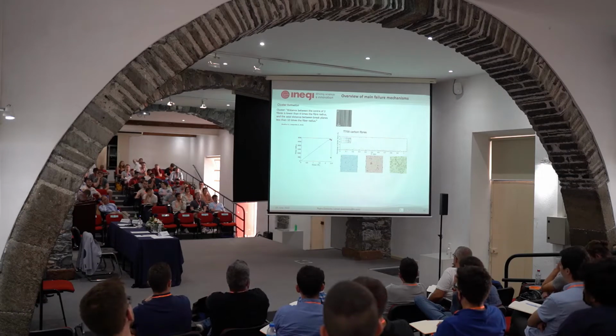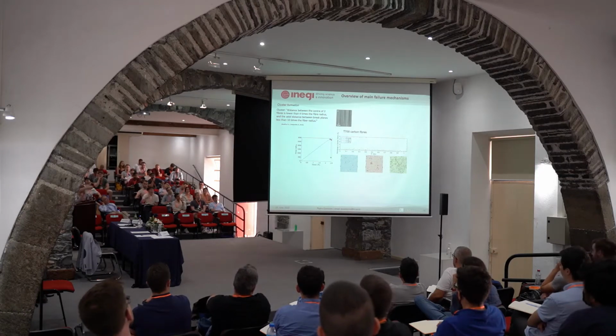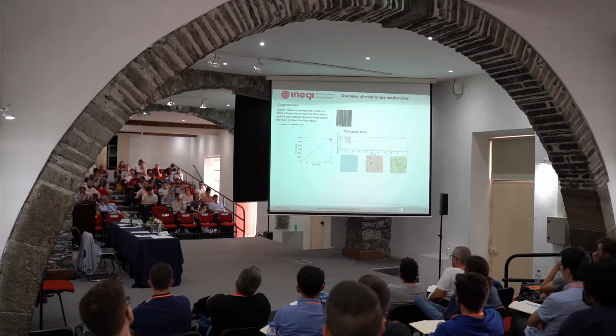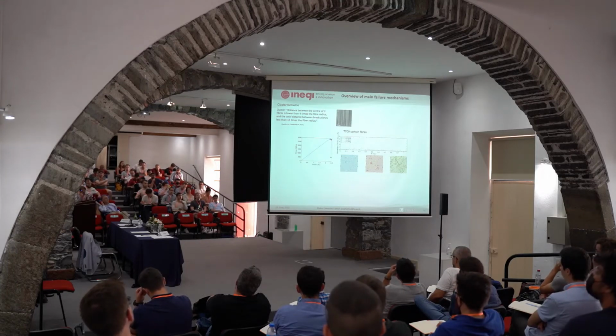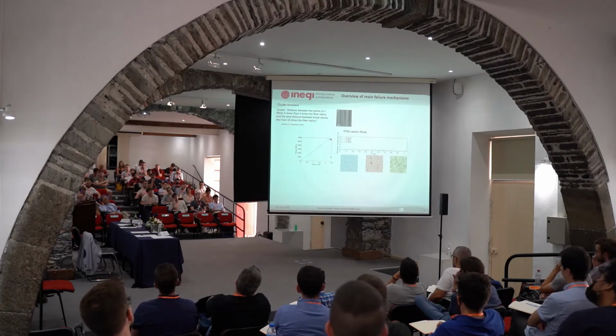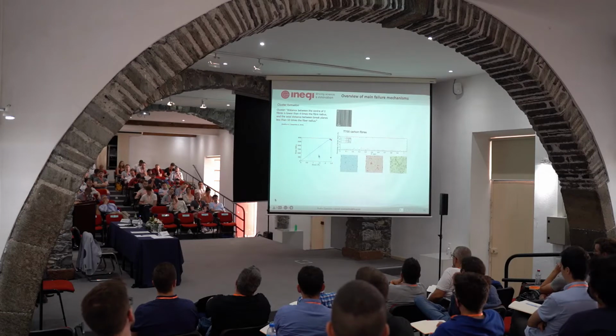So what you can see, even from that picture that was obtained using the synchrotron, is that what you get are individual fiber breaks that are not necessarily all in the same plane. They form a cluster, and when the cluster reaches the critical dimension, you get catastrophic failure. And you can capture that from simulation. And actually what I like about this representation is that you can see from computational micromechanics the phenomenon of localization of damage. Because what you see here is stress versus strain. And here I have 3 points with 3 colors.